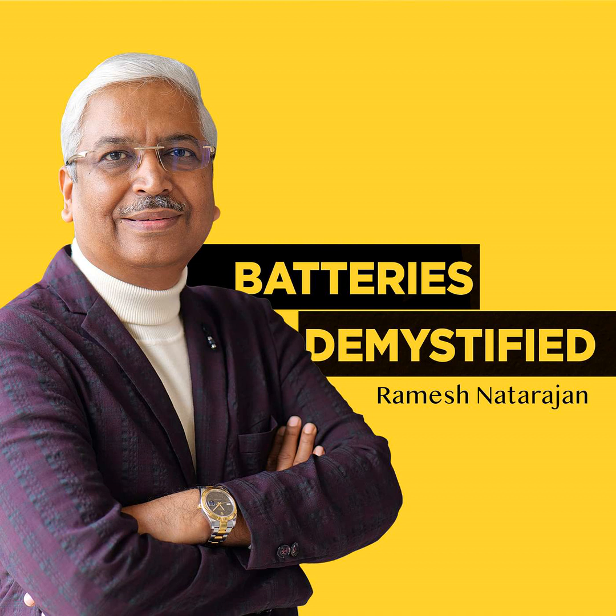So what we see from our testing is that batteries that are made with more lignosulfonates have longer cycle life than batteries that are made without or with smaller dosages. During the presentations yesterday, I showed a slide where Vanisperse A was dosed at different concentrations, and then the lifetime of that battery was tested. And we saw the battery's longest lifetime occurred when a dosage of 0.35 weight percent Vanisperse A was used, which was higher than what we saw for the maximum performance for cold crank or discharge capacity. So it's purely based off of the battery testing we've done, and not really grounded in any sort of mechanistic understanding.